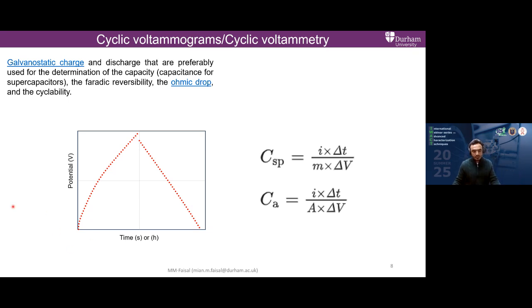This is just one specific example. It is not universal for any material or every material. So you can get different responses. For example, the GCD might have some plateaus, and those plateaus actually resemble the oxidation peak which we saw here. So if your GCD does include some proper plateaus, that gives you similar information to what you received from the cyclic voltammogram, but in the GCD it will be in terms of plateaus.